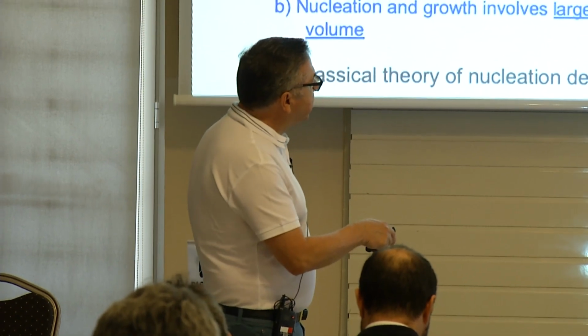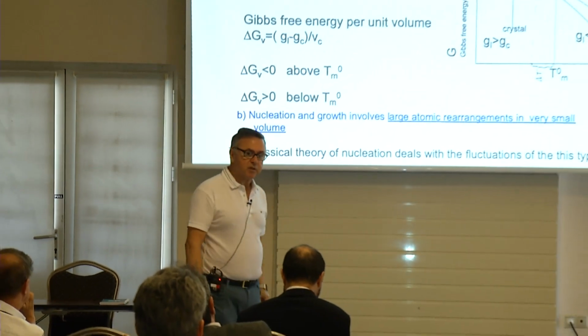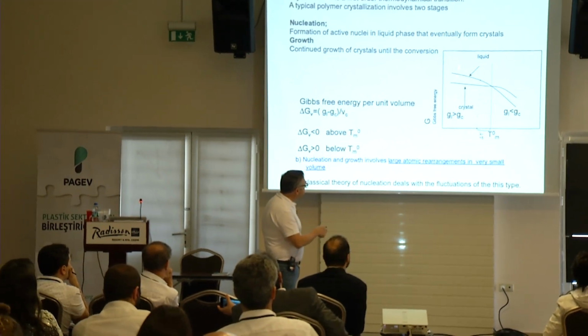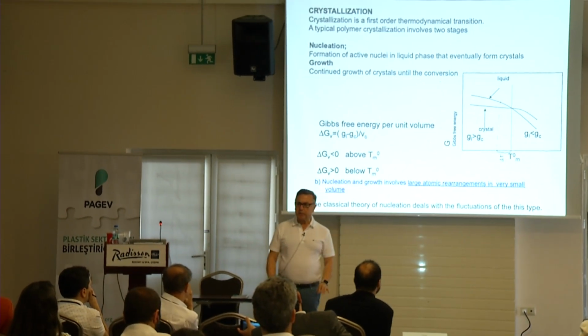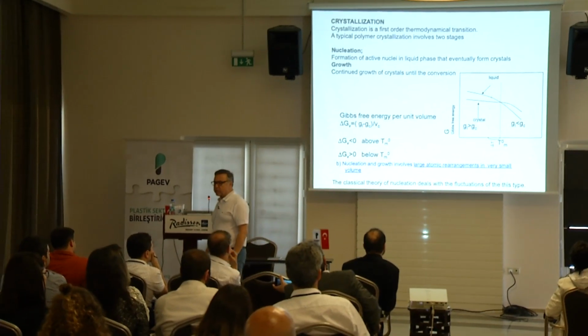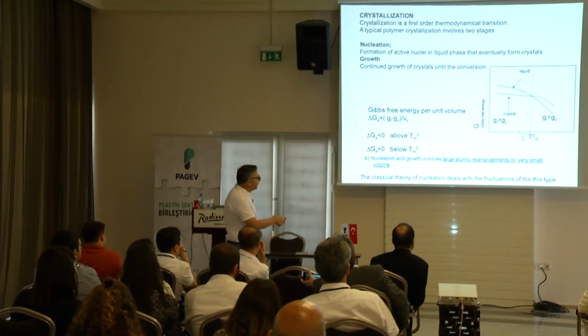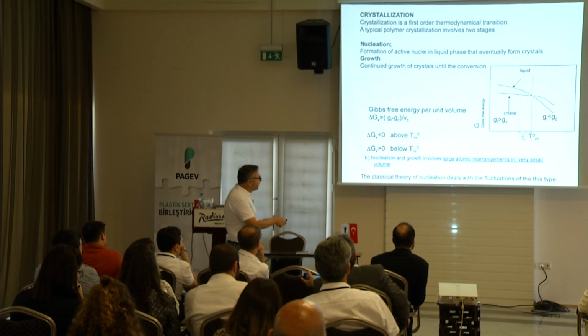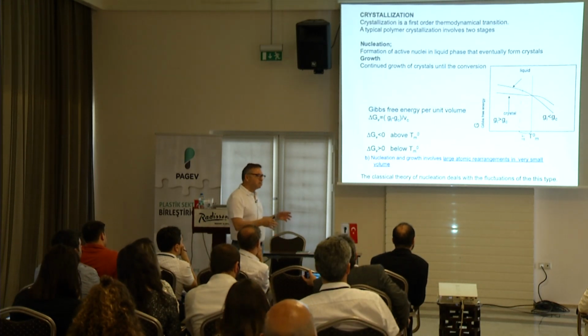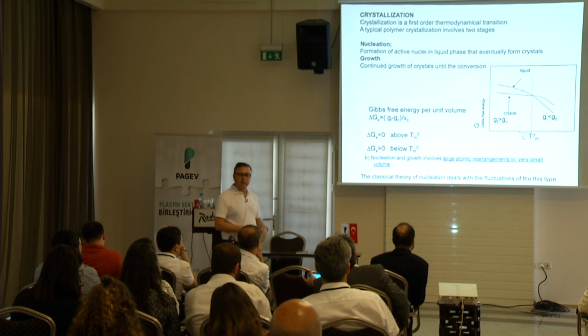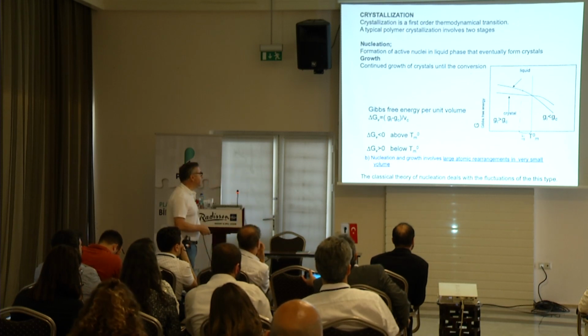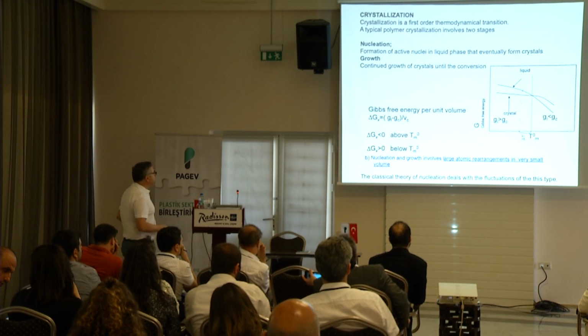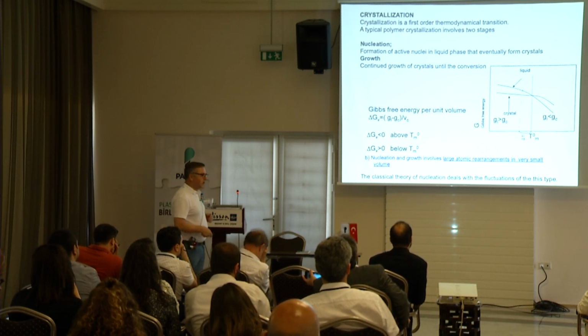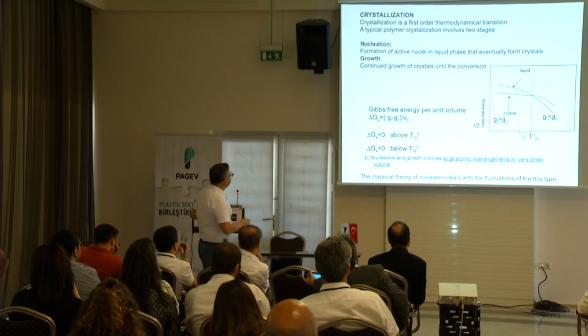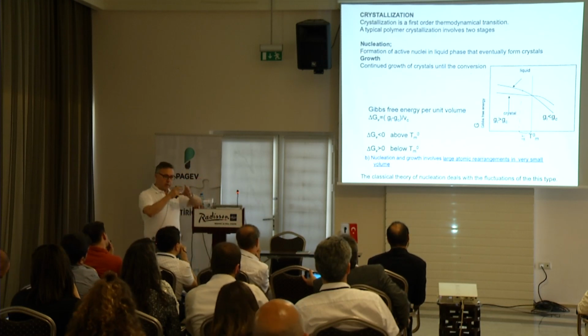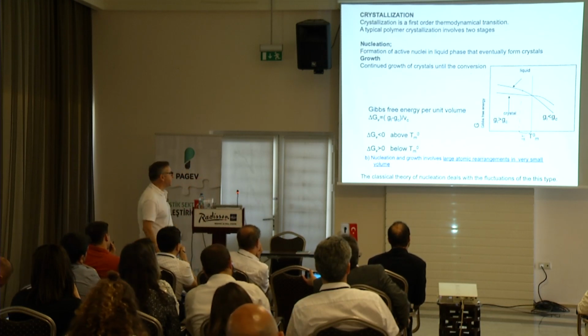The closer you are to the equilibrium temperature, the smaller that driving force gets. The larger the difference, the bigger the driving force. Very simple, thermodynamically. So material really wants to go into the crystal state when you are over here. If it is closer to here, it says, OK, I'm going to mosey along and get there much more readily. OK? So we deal with the nucleation process, crystal formation, right? And the growth. You form, and then you also have a growth process happening.